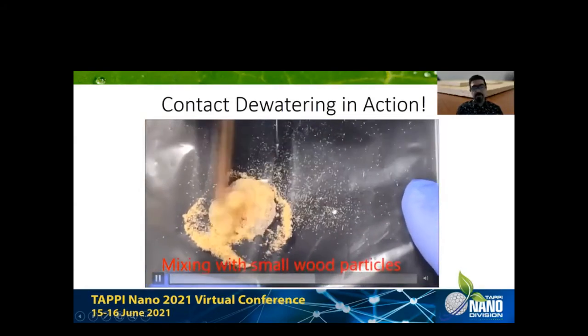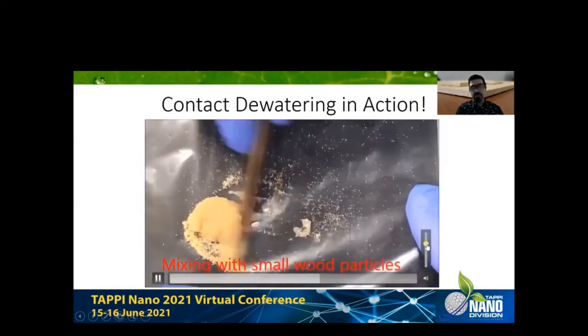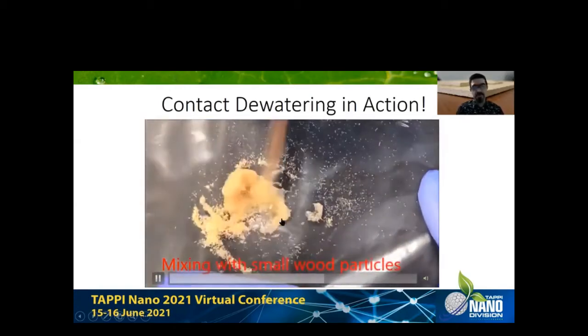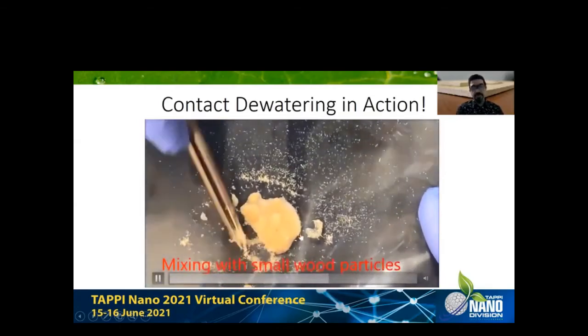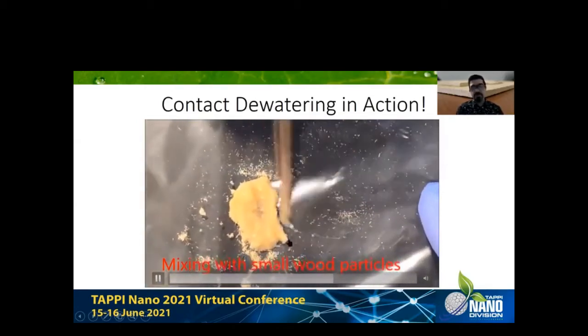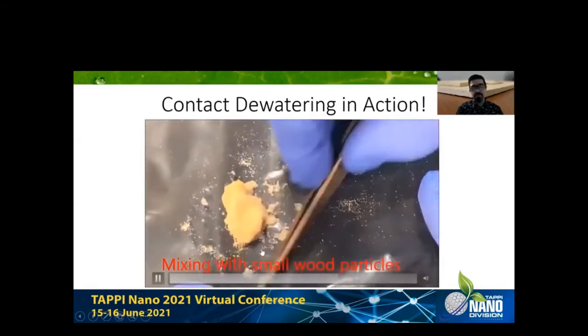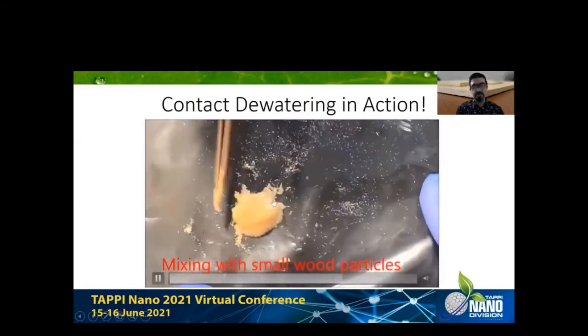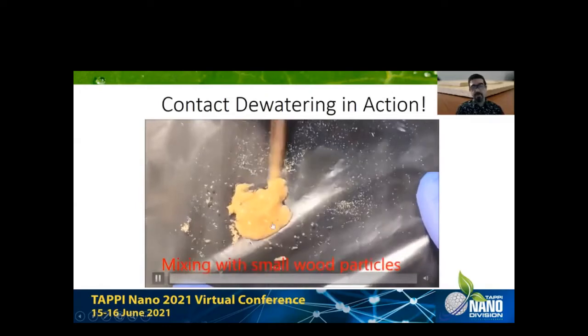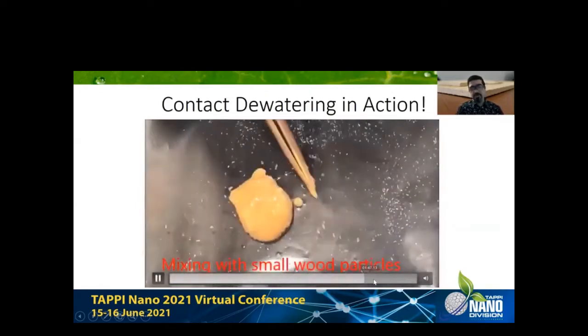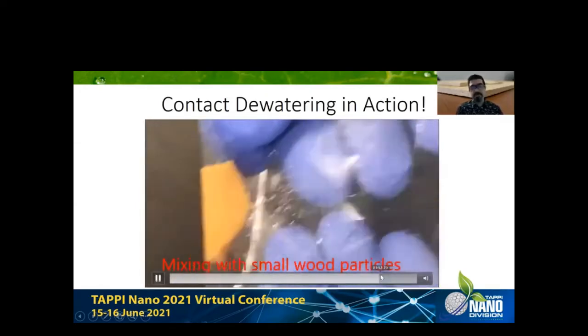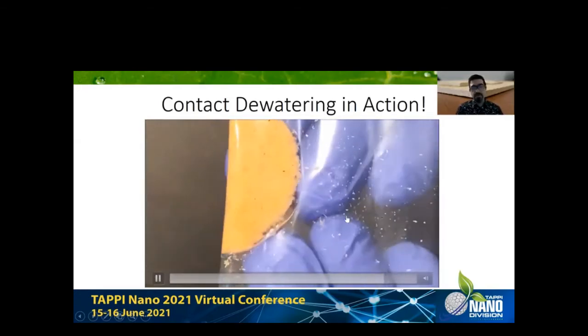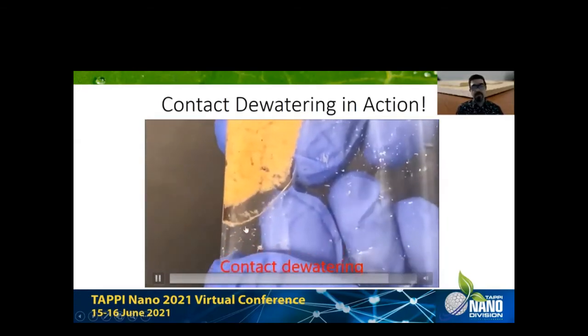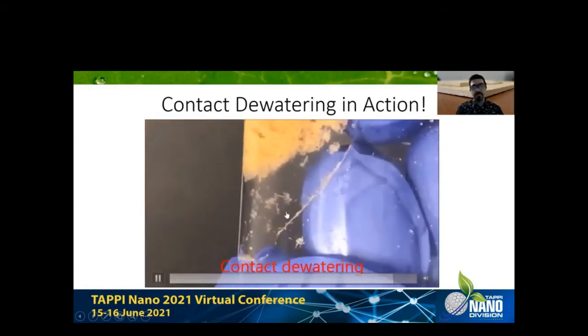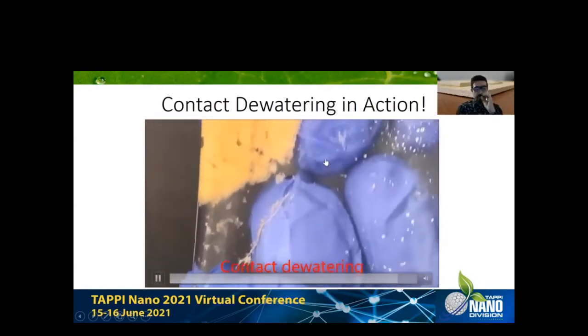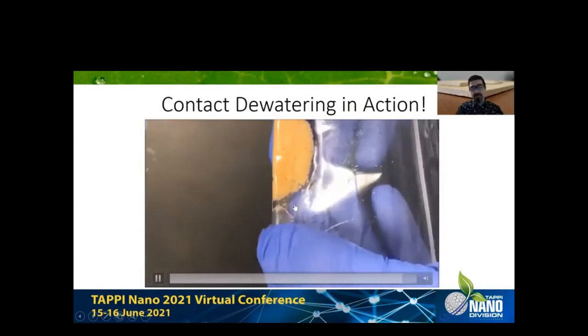Now, if you switch those larger particles with these smaller particles, the amount of nanocellulose is the same, the solid content is the same, the amount of wood is the same. The only difference is the particle size and therefore the specific surface area of the wood particles. If you do this now and do a similar thing and try to get the water out, voila, this is what we call contact dewatering. And you see that water is actually getting separated so easily, and this water actually doesn't have any nanocellulose in it.